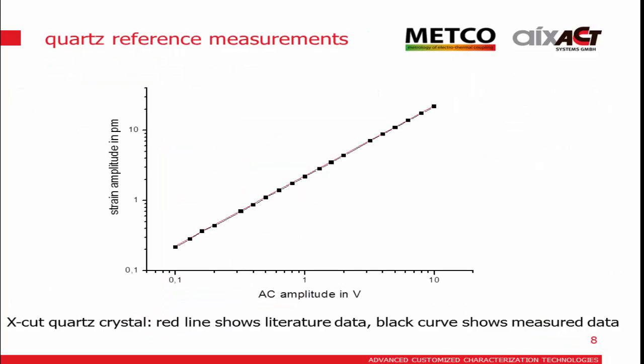What we typically use is a quartz crystal for verifying the measurement. This has been used from the beginning to monitor the performance and resolution of the interferometer. We have around 2.2 picometers per volt, and this is how we check the resolution of the system - we can go down below picometers in the system resolution.